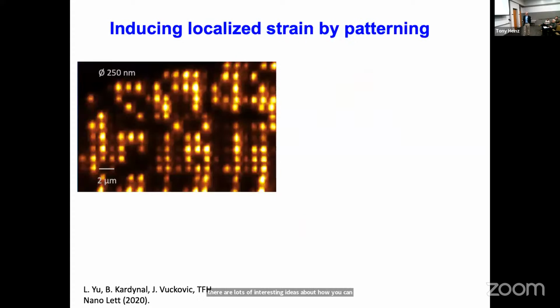So why would you want to do this? Well, this is an illustration where we made holes in different spots, and we pressurized the materials. And then we see the optical emission is localized at these holes. Well, actually, it's not totally localized at the holes, but we filter the emission. We look at the longer wavelength component, and then we see the emission that's coming from the region of reduced band gap. It's also the case that actually the excitons move around and they fall into these traps. So both of those things are going on.